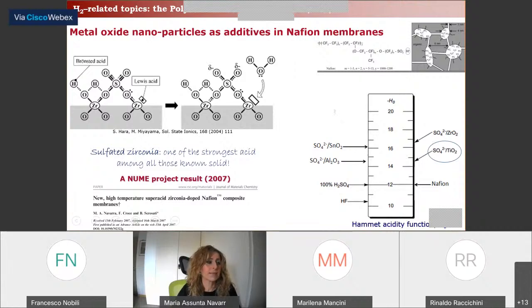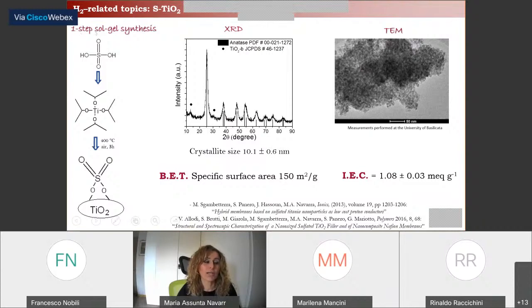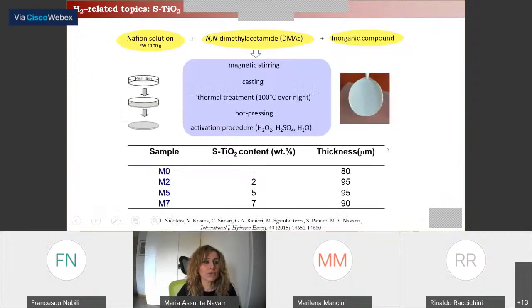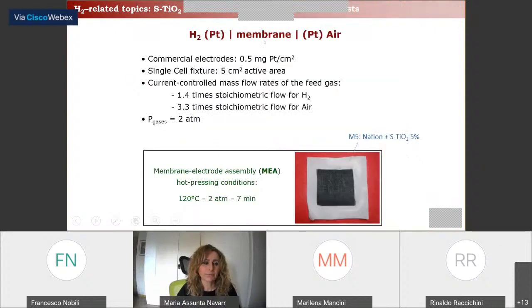We synthesized this compound through a convenient one-step sol-gel synthesis, resulting in anatase particles with a very homogeneous round-shaped morphology, a good surface area, and a very high ion exchange capacity, even higher than Nafion itself. These particles were used to realize nanocomposite Nafion membranes. Of course, in order to investigate the effect of the filler, several compositions were studied, and these membranes were used as electrolyte in hydrogen-air fuel cell devices by adopting commercial benchmark platinum-based electrodes.